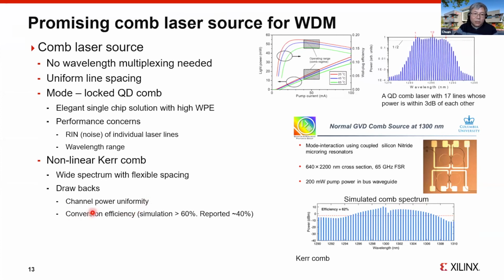And the challenge here is the line power uniformity. You can see right in the middle of the range, you have a couple of lines with low power. This is actually a simulated result. According to the simulated result, of course, you pump this device with a CW laser, and it's being converted into a comb. So there's a conversion efficiency. The reported highest conversion efficiency is about 40%, and according to the simulated result, you can go above 60%. But nevertheless, you lose 50% of the power because of this conversion efficiency. So the wall plug efficiency in the end may have a fundamental limit.